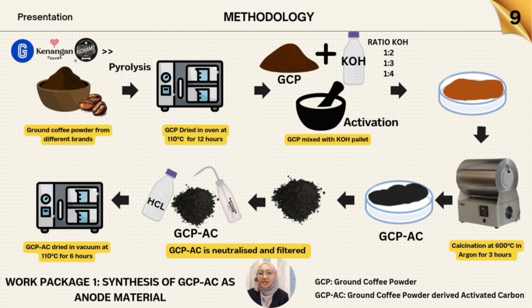This process began with drying the ground coffee powder, followed by pyrolysis to remove volatile components, then mixing them with KOH in different ratios, and using calcination at 600 degrees Celsius in argon gas to activate the carbon. So after the calcination, the samples were neutralized with hydrochloric acid, filtered and dried, resulting in GCP-AC samples ready for testing.